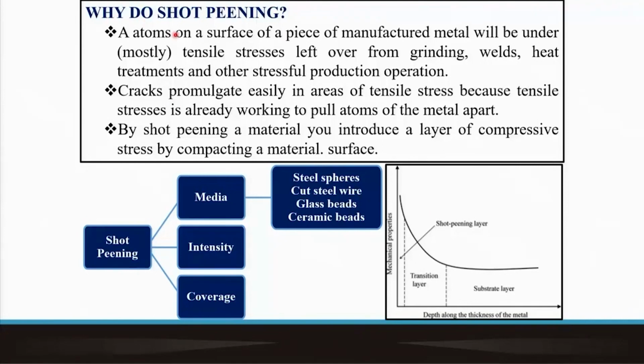Now, as I said, why do we do shot peening? We do it basically to create residual compressive stress. If you think of a mechanical property, then these properties can be very effective only up to a very limited depth from the surface. If we are talking about residual compressive stress or surface hardening effect, please remember there is no thermal component here. Otherwise, the plastic strain that we develop will be dissipated through recrystallization or some other kind of stress relief operation. So this is done entirely at room temperature, or even if there is an adiabatic temperature rise, it won't be more than a few degrees or a few tenths of a degree.